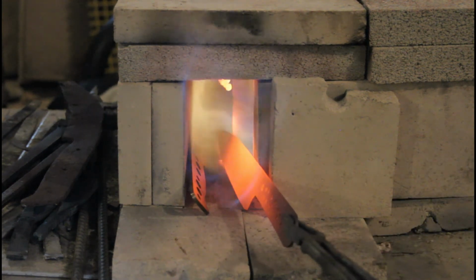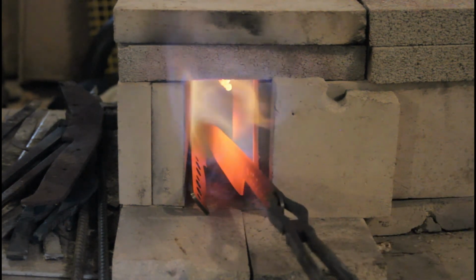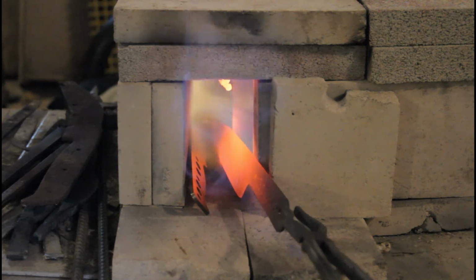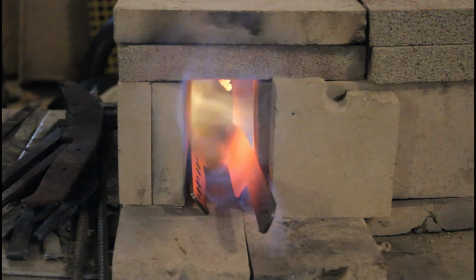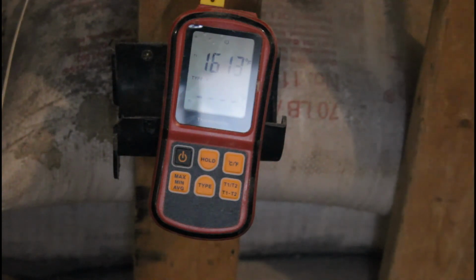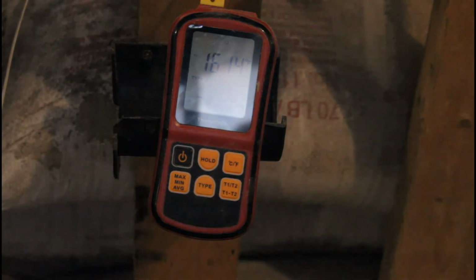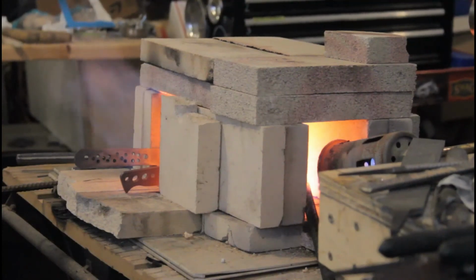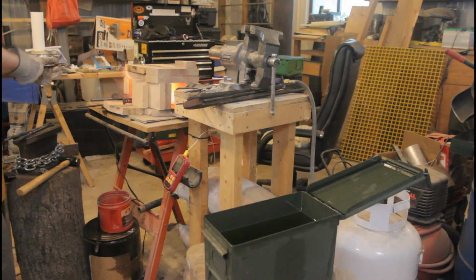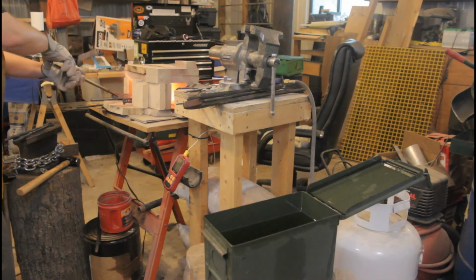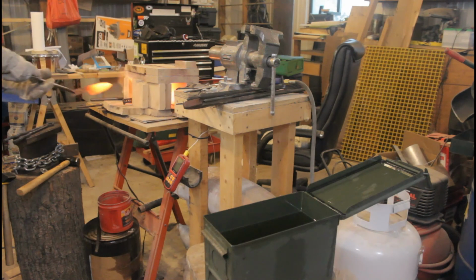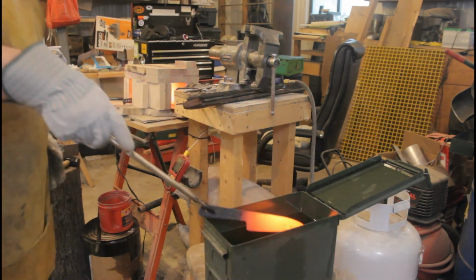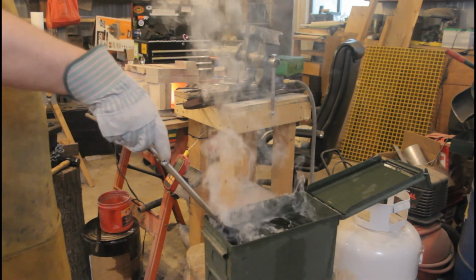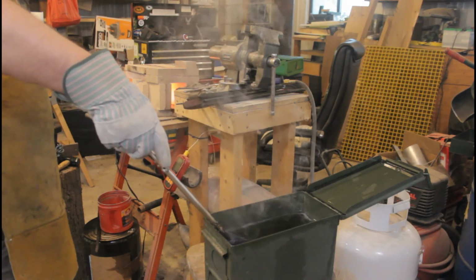But in general, I'm trying to slowly heat the steel up to about 1560 degrees Fahrenheit. Hold it there for about 5 minutes, then quickly ramp the heat up to between 1940 and 1975 degrees Fahrenheit. Then hold it there for a further 15 minutes. Then I'm going to quench it in pre-warmed, somewhere above 100 degrees, canola oil. This method has given me pretty good results in the past.